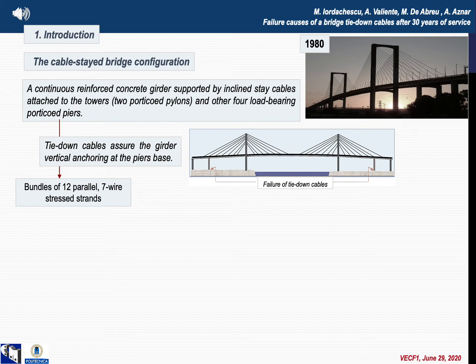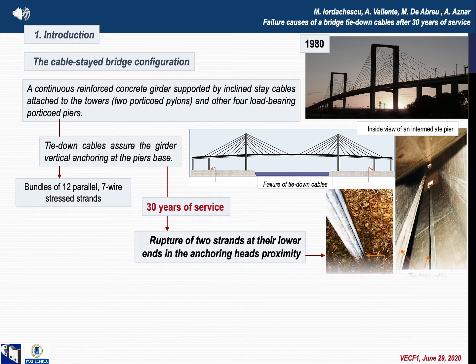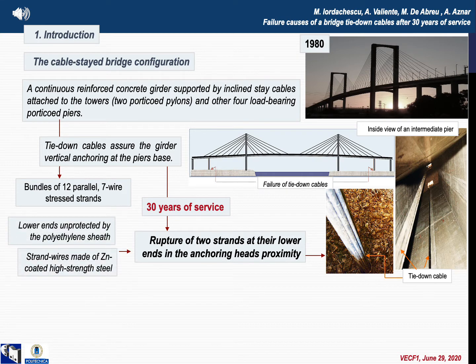The cables are bundles of 12 parallel 7-wire stressed strands mounted inside the piers. After 30 years of service, the rupture of two strands occurred at their lower ends in the anchoring head's proximity. The site inspection revealed that parts of about 0.5 meters at the strand's lower ends, starting from the exit of the anchorage system, were unprotected by the polyethylene sheath. The error attributed to the mounting of the anchorage system remained undetected over time.